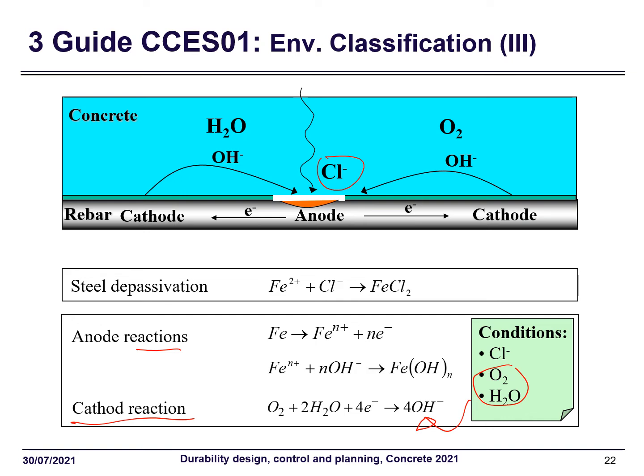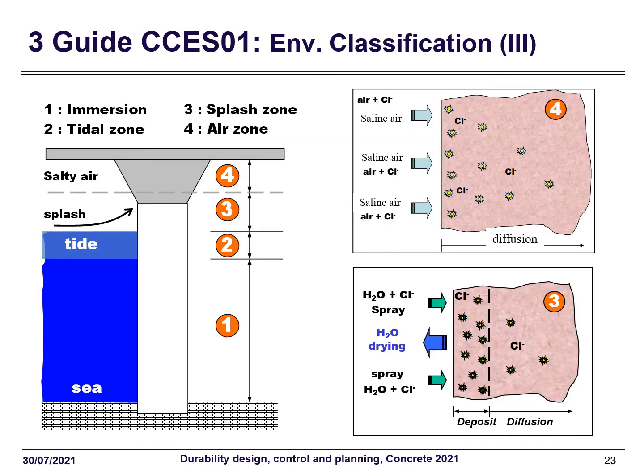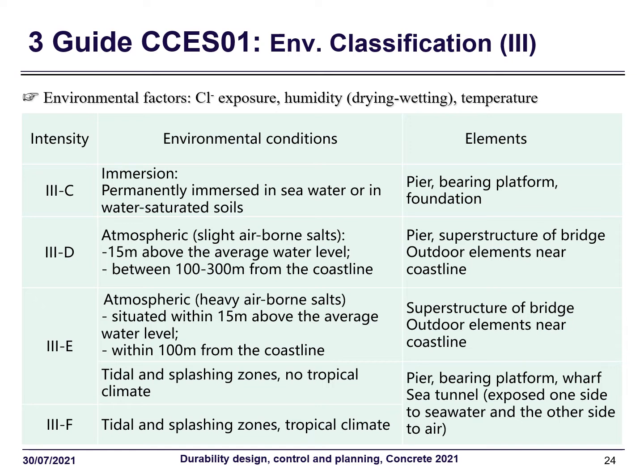reaction possible. So if we apply this mechanism to a marine exposed structure, we can see that in the splash zone of exposure, at the surface we have a drying and wetting action, leaving very high chloride concentration on the surface, and in this zone we also have the alternative availability of oxygen and water, which are very favorable to the corrosion.